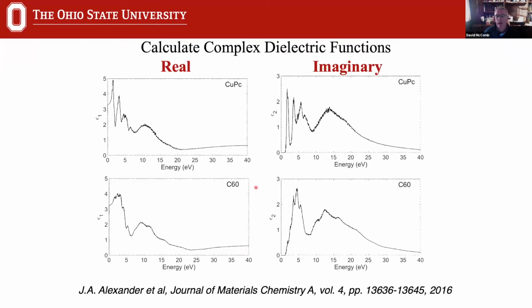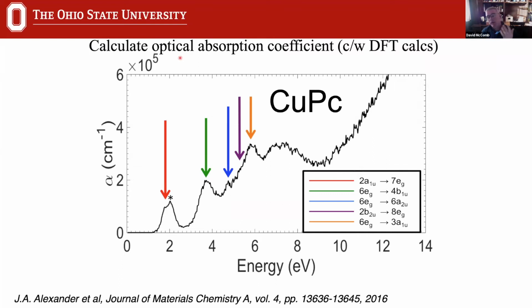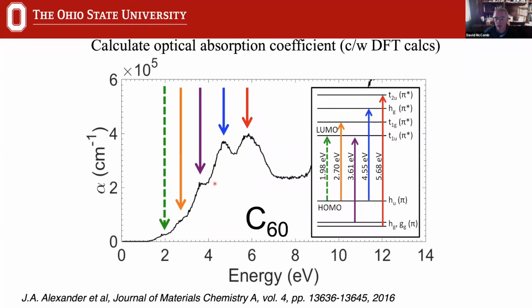We can get to our complex dielectric function through processing, and this takes us to the imaginary part on the right-hand side. So this is the imaginary part of the dielectric function for those two phases. And then you could even take this and calculate, for example, things like the optical absorption coefficient. This is where we do this for copper phthalocyanine, and that means that now we can compare the peaks in this low energy part of the spectrum to the predicted excitations between highest occupied molecular orbitals and lowest unoccupied molecular orbitals. And these predictions from the MO theory fit extremely well with what we see experimentally in the case of copper phthalocyanine, and similarly in the case of C60. And so we're able to get to these low energy regions and to do this kind of work because we were able to monochromate and get that nice zero loss peak.